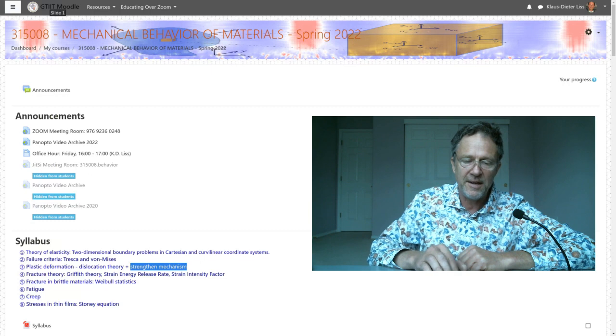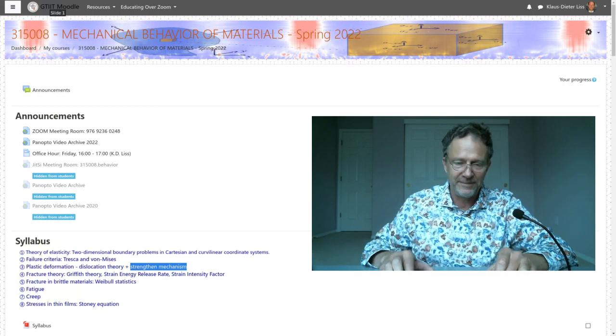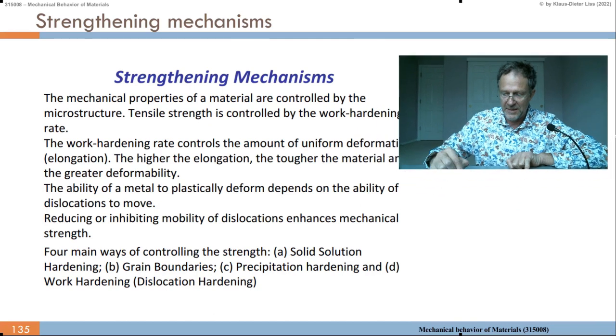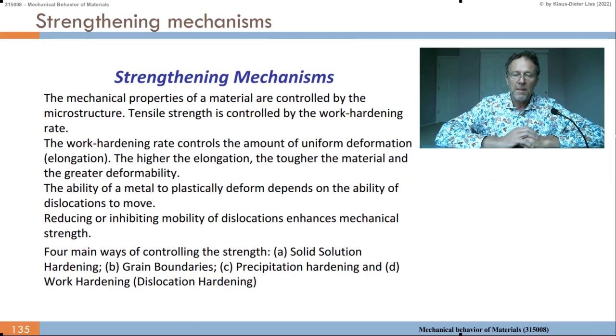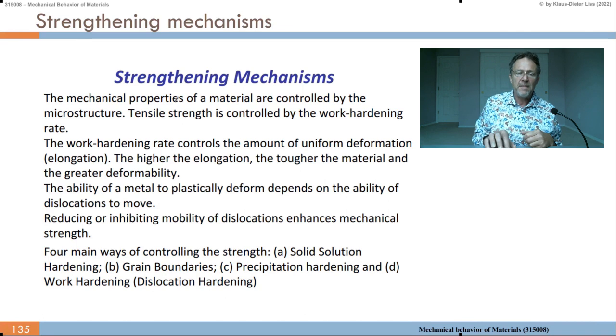So here let's go into the strengthening mechanisms by dislocations. What are strengthening mechanisms? The mechanical properties of a material are controlled by the microstructure. And we heard already the tensile strength is controlled by the work hardening rate. It means we plastically deform a material and then the material becomes harder, it becomes stronger. And this is due to dislocations. The work hardening rate controls the amount of uniform deformation in the elongation. The higher the elongation, the tougher the material and the greater the deformability.